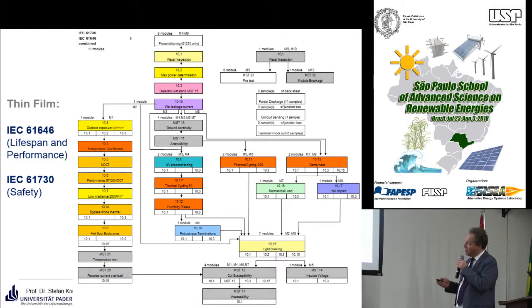This is a procedure called light soaking. You keep the module for 48 hours in a box with a lot of light, then measure the power output, then put it back in the box of light and see whether it changes in performance due to the light treatment. And this you do only at the end because it can take a week or so to do the test. And then it receives that seal, the IEC 61646.